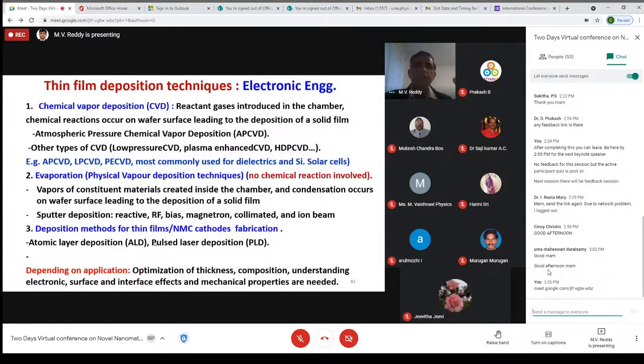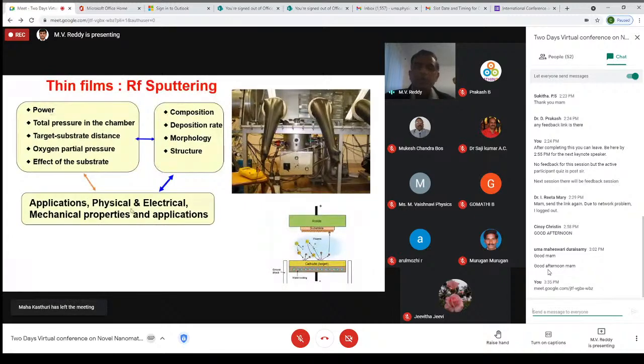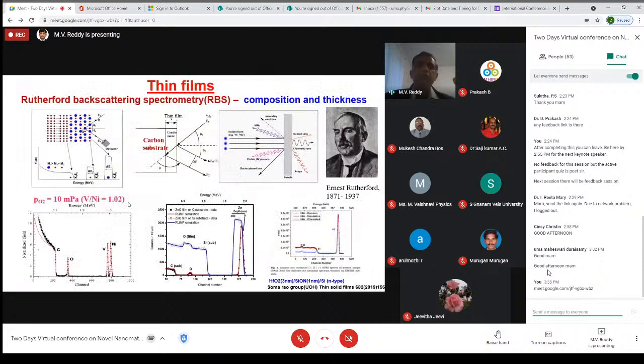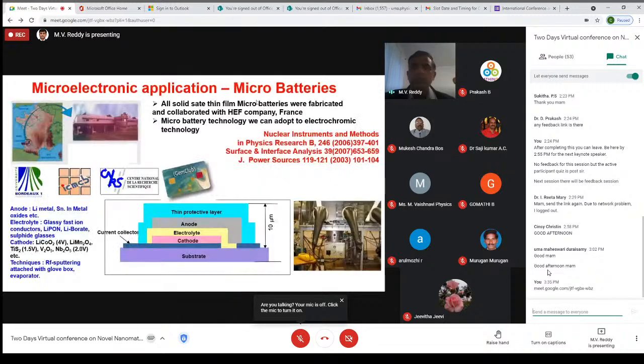Since physicists are here, with thin films we can also get results using various techniques. Since I don't have time to discuss them, we can do chemical vapor or physical vapor deposition techniques. Among them, with RF sputtering, we can control various physical parameters, composition and structures. Rutherford backscattering is a very useful technique to know the composition and thickness. Usually when a helium beam is incident on a thin film, by knowing the backscattered energy, which is proportional to the atomic mass, it means the higher the mass, the higher the energy channel number. So by using simulation, we can know the composition and thickness, etc. Again, using the sputtering technique, you can do all layer-by-layer thin film technology.